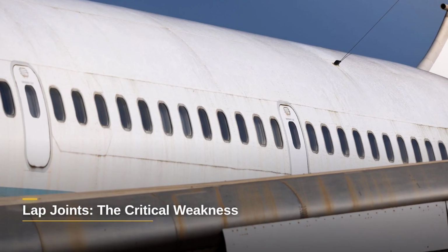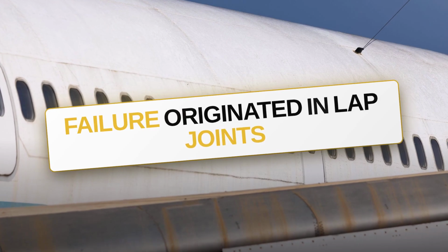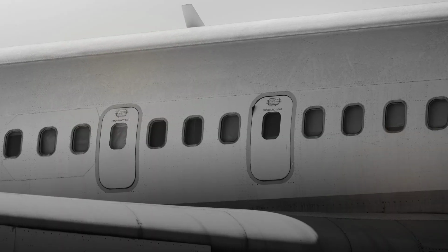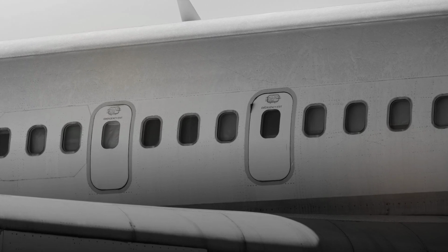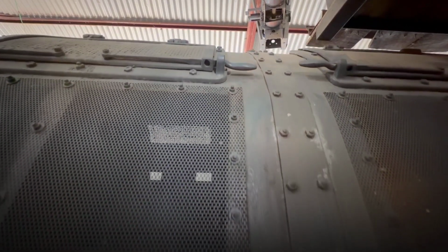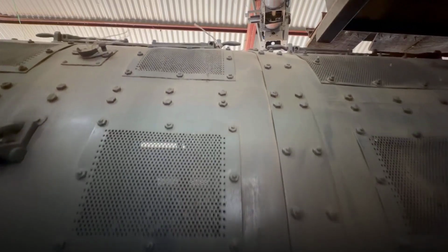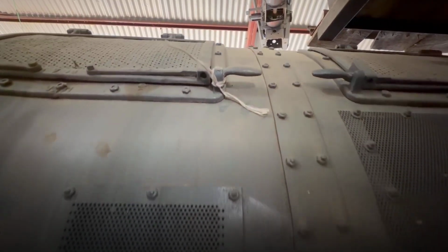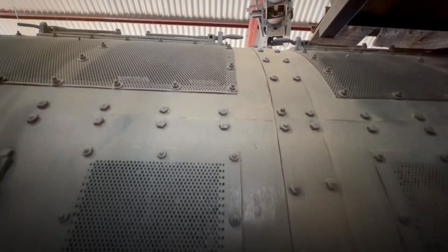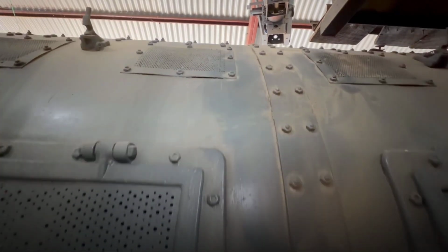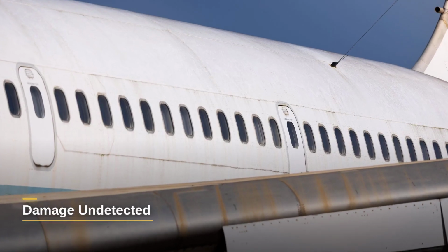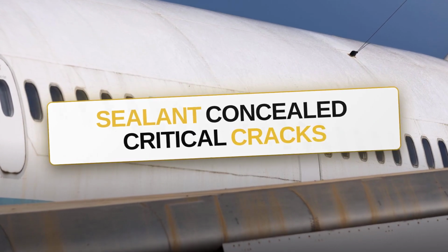The fuselage of the Boeing 737-200, like many aircraft of its era, was constructed from multiple aluminum alloy sheets riveted together at lap joints. These joints are crucial structural elements, providing continuity and strength to the pressure vessel. On Flight 243, the failure originated in these lap joints. Specifically, multiple site fatigue fractures developed around the rivet holes within the upper rows of rivets. These tiny fractures, born from cyclic stress and exacerbated by corrosion, were the invisible fault lines that would ultimately tear the aircraft apart. Despite maintenance inspections, these critical fatigue cracks remained undetected.